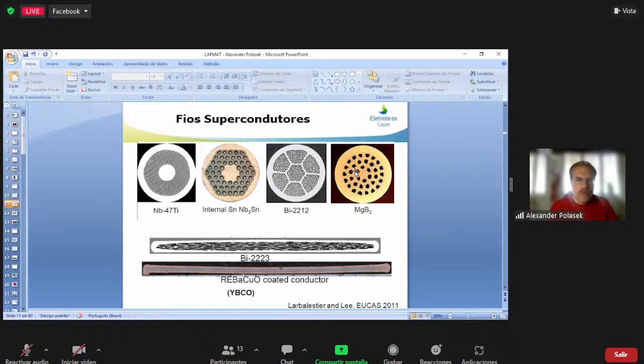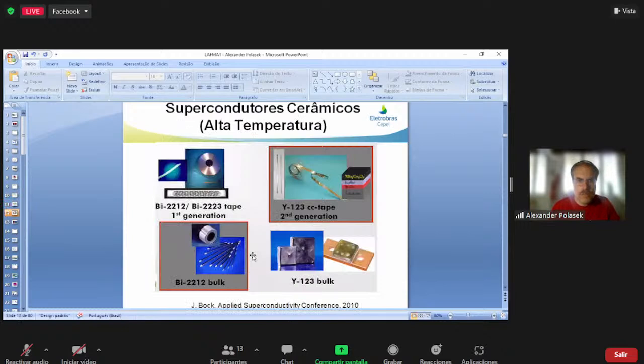Round wires are preferred by the industry and for making coils, etc. But because of anisotropy, in the case of these two materials below, you need tapes. And you can see here some other pictures of the YBCO second generation tapes, which are the most important materials for power applications nowadays. And there are well-known bulk materials, the BSCCO, bismuth first generation wires, and the bismuth bulks as well.